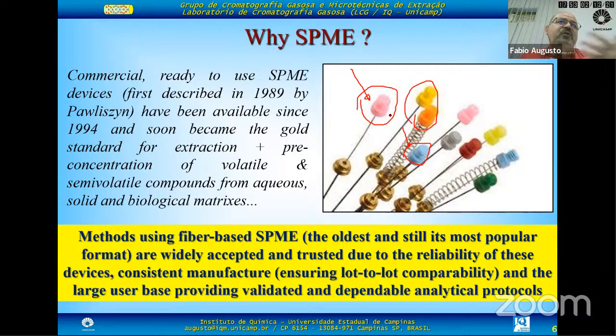PDMS DVB is more selective towards more hydrophobic compounds, and it's more efficient overall, because you have a small fraction of a solid adsorbent. Solid adsorbents tend to be more efficient. For coatings which are polymeric, so PDMS, of course, PDMS is non-polar, so you have a very high affinity for non-polar hydrophobic compounds, and depending on the coating thickness, you have more or less efficiency.